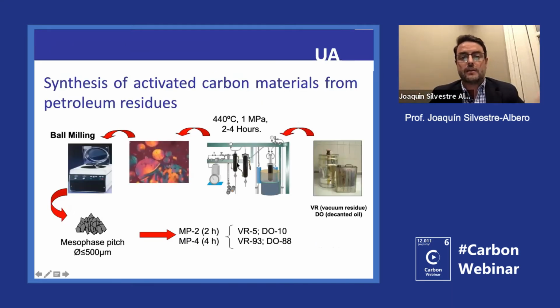So that was our main goal. We wanted to design carbon materials with a high surface area and with the smallest porosity possible. So at this time, we were very familiar with petroleum residues. In this case, we decided to use two different residues, vacuum residue, VR, and decanted oil. And the first thing we did was a pyrolysis step at 440 Celsius, changing the time of the pyrolysis, so that we could modify the mesophase content of the mesophase pitch.